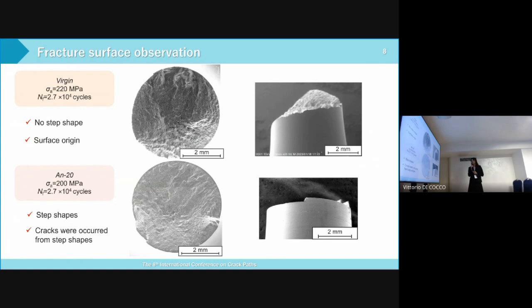Next, to investigate the fatigue fracture mechanism, we performed fracture surface observation on each specimen. These are the results of virgin and AN20. First, regarding virgin, it exhibited surface origin fatigue fracture, and similar results were obtained for all tested specimens.